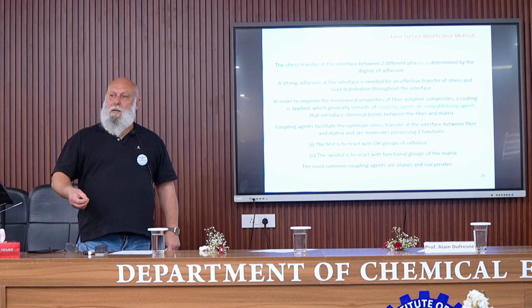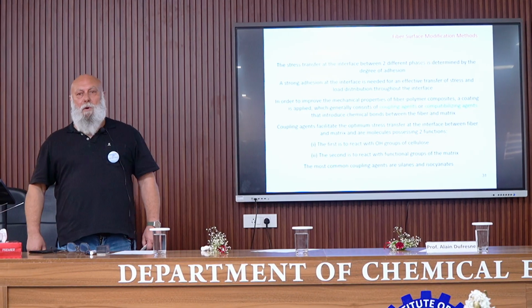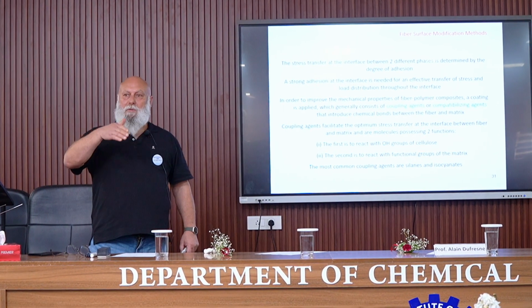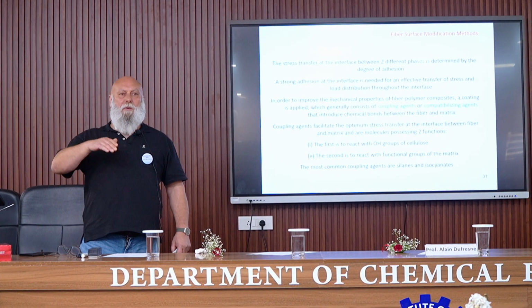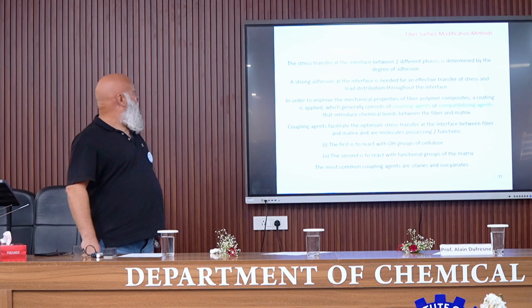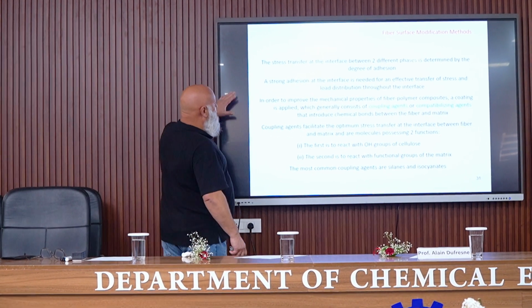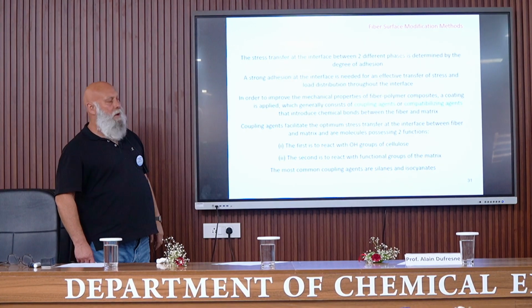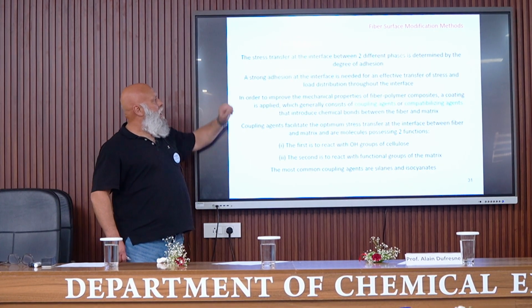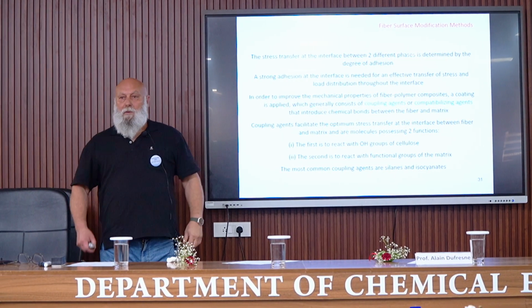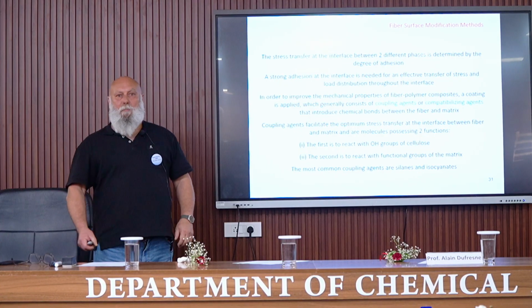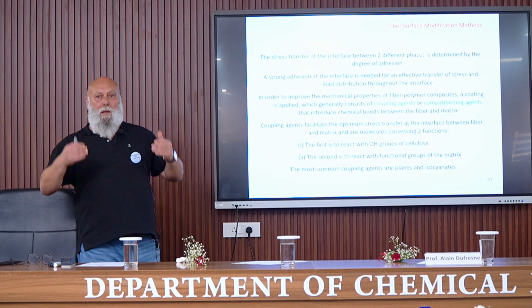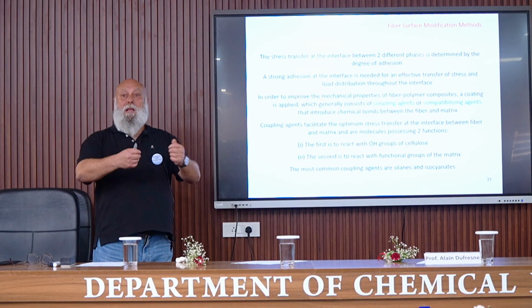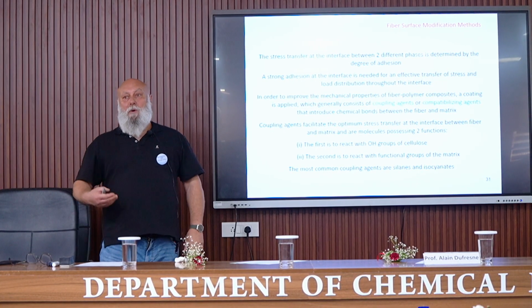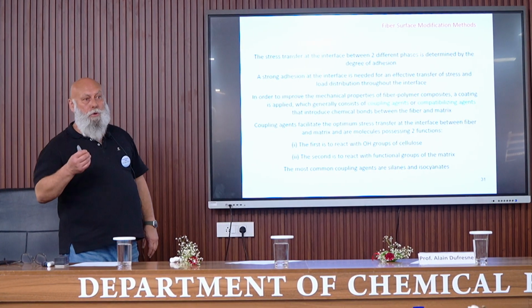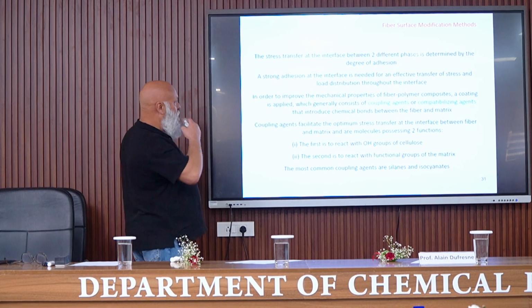So meaning that generally the treatment is performed on natural fibers. And so it consists in turning the hydrophilic natural fiber to hydrophobic. So I mentioned previously that one important parameter to have an efficient reinforcing effect is the stress transfer at the interface. So the stress or the load is applied to the matrix, which is the outer part of the material. It is transferred to the fiber that can support higher load. But for this, of course, it's necessary to have a good degree of adhesion between the fiber and the matrix.